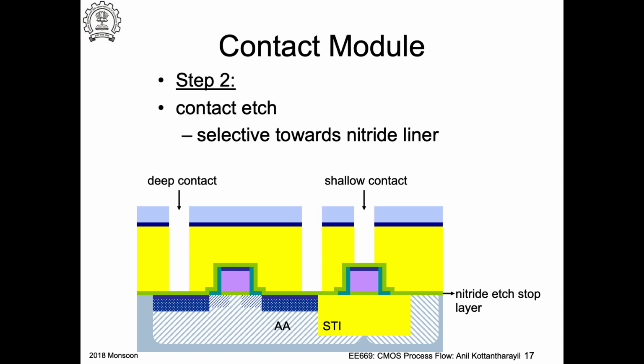Why is this important? This is important because if you look at the source drain region, right, you have to etch a fairly thick phosphosilicate glass. But you look on the right hand side, yeah, the etch has to stop on the polysilicon. So that is a shallow region. Yeah? Now you can see that as you etch, the plasma chemistry would actually see the top of the polysilicon on the right hand side first. But I need to contact the source drain also. So as I continue to etch, so that I etch the phosphosilicate glass till the source drain contacts, the polysilicon top is also seeing this etch chemistry continuously, right?